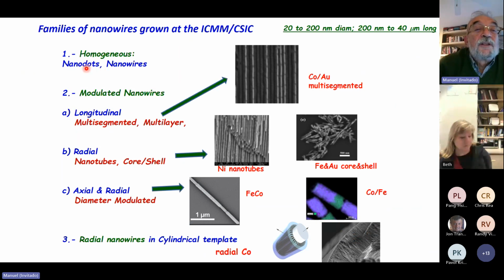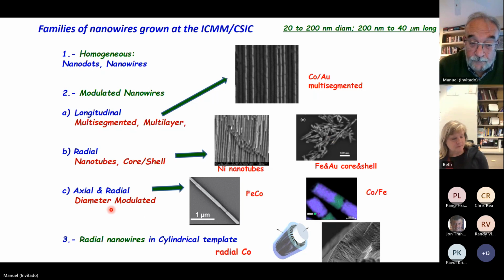So we can prepare in Madrid different families of nanowires. We can prepare homogeneous nanowires with the same composition and diameter along the whole length, but we can also prepare modulated nanowires. These modulations can be in the longitudinal direction. For example, you see here an image with cobalt-gold multisegmented nanowires. The modulation can also be in the radial direction, so we can get nanotubes or core-shell nanowires. And the modulation can also be in diameter. You see here an image of an individual nanowire with alternating segments with large and small diameter.